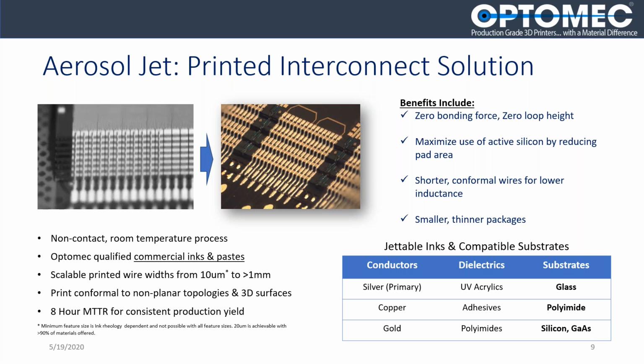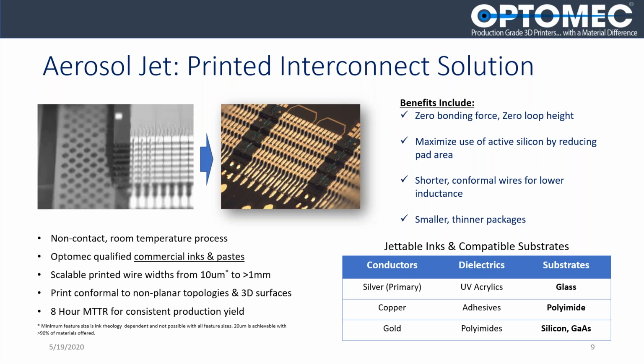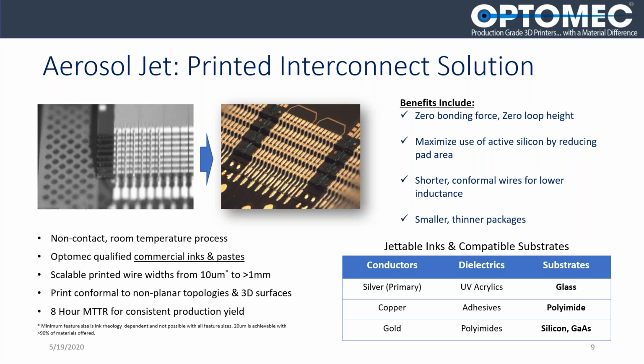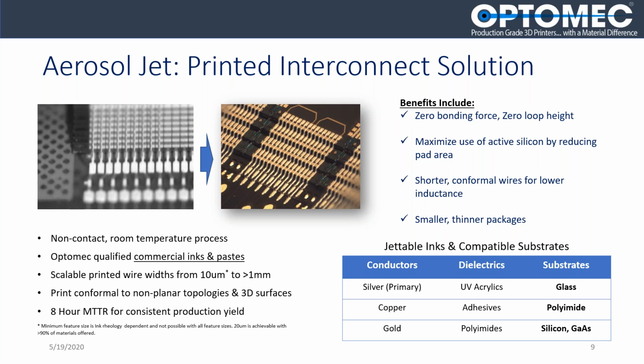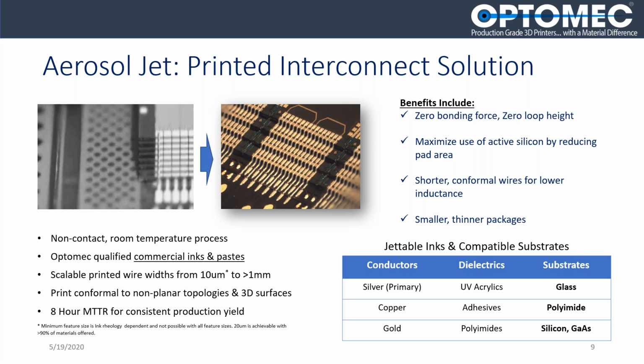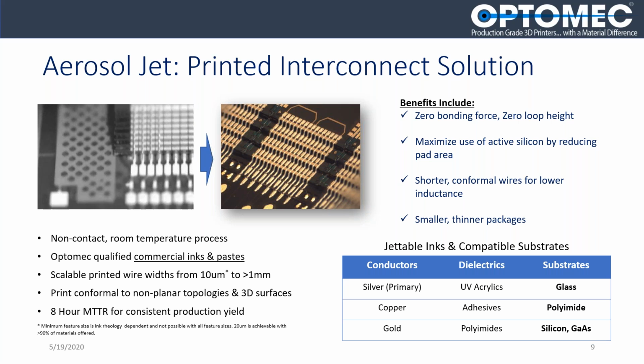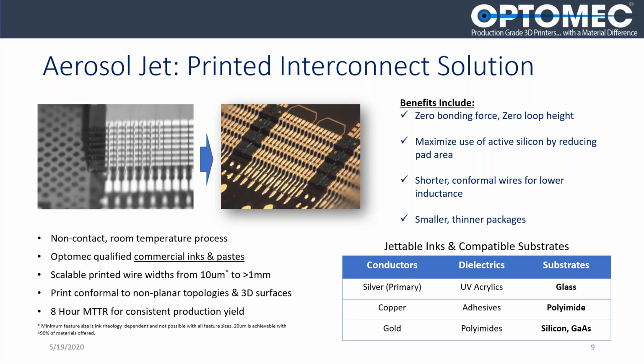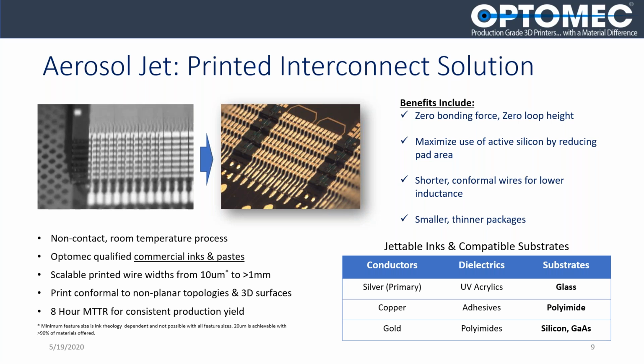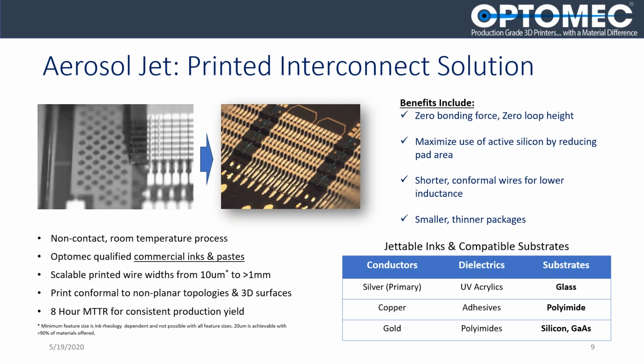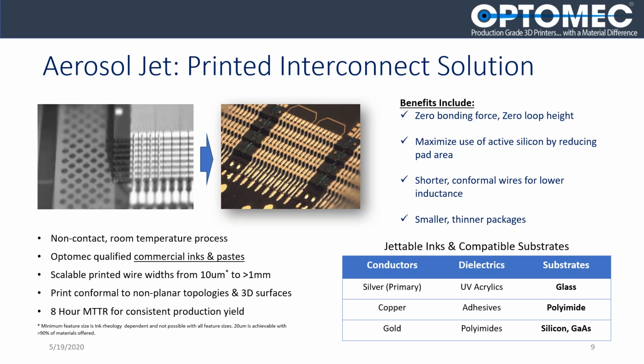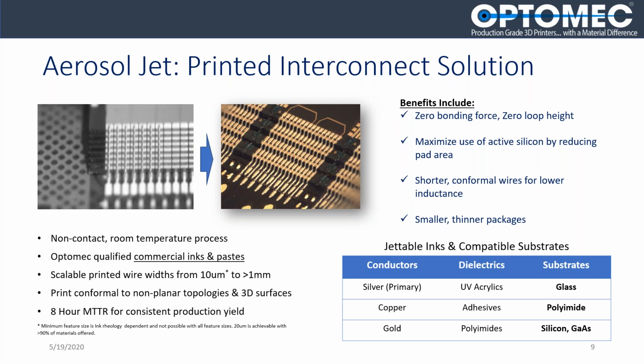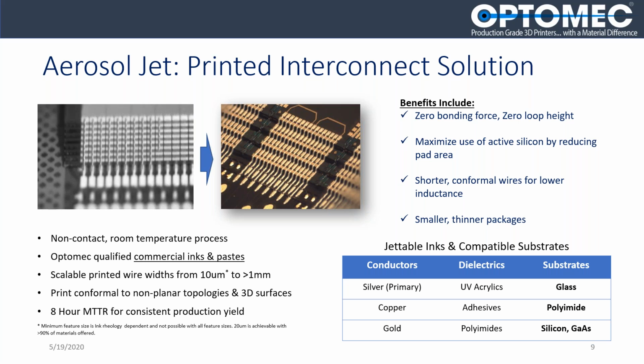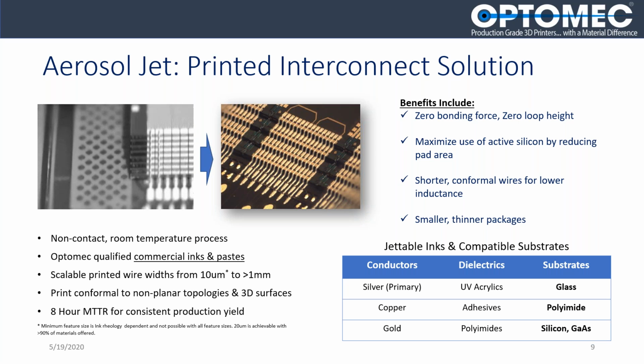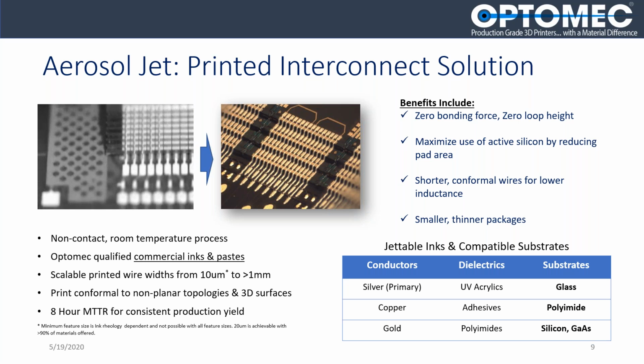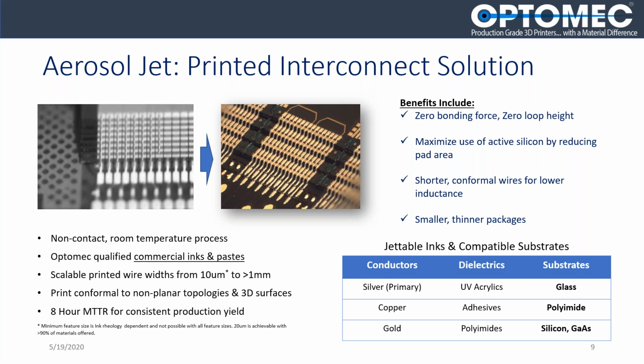So the 0 bonding force is really valuable because it allows you to work on very fragile substrates like gallium arsenide. The fact that we're able to print these small wires and we don't need to leave landing area for the bonding capillary allows us to make the pads smaller. And because we're printing conformal wires, they're shorter, meaning that they have lower inductance, and we're able to do a better job at impedance matching with our interconnects. And this all results in smaller, thinner, and effectively cheaper packages, which I think the examples will highlight directly to you. And in the lower right-hand corner, just a highlight of the different types of conductor, dielectrics, and substrates we consider to be within the package solution of printed interconnects.